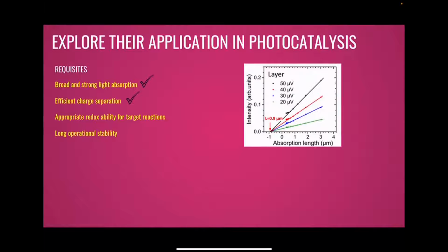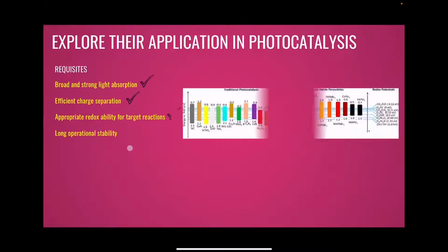They intrinsically have very good charge carrier separation efficiency. Of course, redox ability for the target reaction. Here you see a plot of the redox potentials of relevant photocatalytic reactions such as CO2 reduction, hydrogen photogeneration, even oxygen photogeneration. And here you see a series of traditional semiconductor photocatalysts currently used, such as titanium dioxide, graphitic carbon nitride. And here you see the band level alignment of some metal halide perovskites. For example, you see here formamidinium lead iodide, FAPbI3, FA is formamidinium. Here you see cesium lead iodide, CsPbI3, and so on. So basically, they have the potential to run most of the relevant photocatalytic reactions.